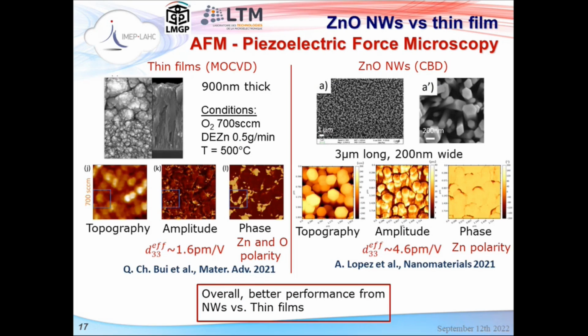And now, how is this linked to the presentation of this morning? This morning, Thomas presented some results of piezoresponse force microscopy. This is not composites, right? This is only characterization on thin films and on nanowires. But what he showed this morning is that in the thin films, what we have measured, or our colleagues measured, is that the thin films have a low piezoelectric coefficient compared to the nanowires, which have a higher one, about, I don't know, 2-3 times higher piezoelectric coefficients. So the effect of the surface traps could also explain this increase in the performance of nanowires compared to the thin films.